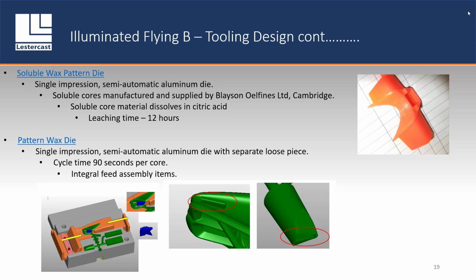And effectively, we get those manufactured. It looks like a normal wax, effectively. And once we've manufactured that, we put it into the wax injection die, and then we inject our casting wax around it. To then remove it, we dissolve it in citric acid, which basically attacks the orange soluble core, but doesn't attack the green wax. So effectively, then we're left with a very complex shape that ordinarily wouldn't be able to be made by conventional tooling means. Leaching time is around about 12 hours.